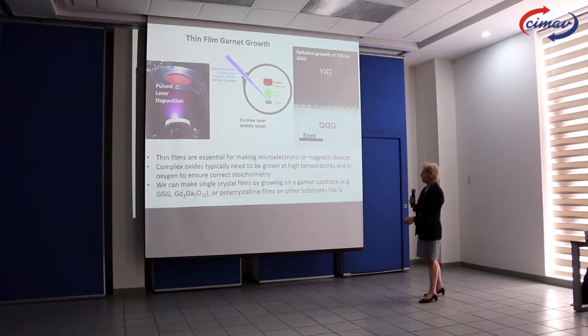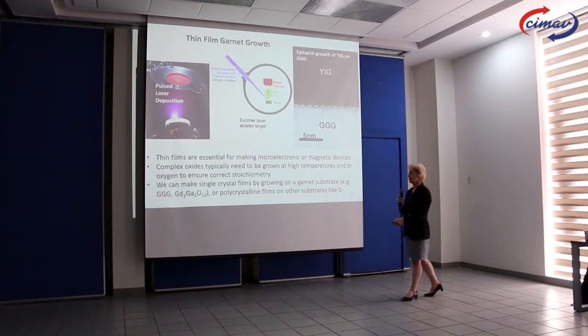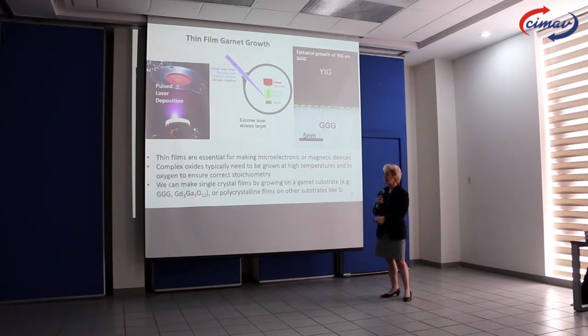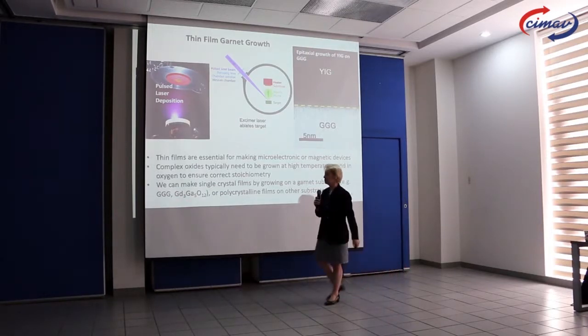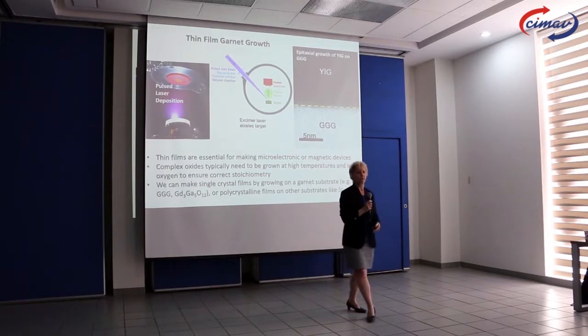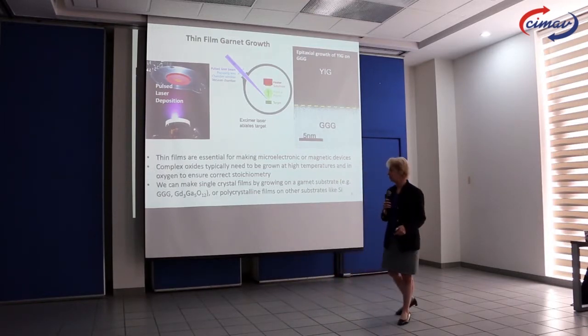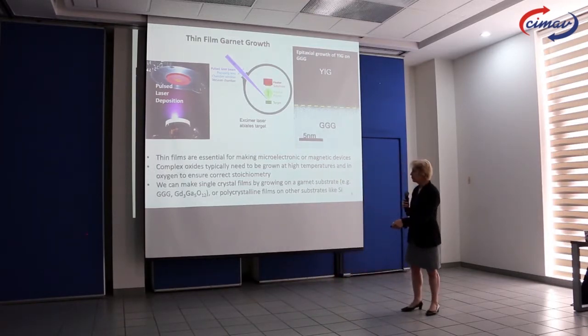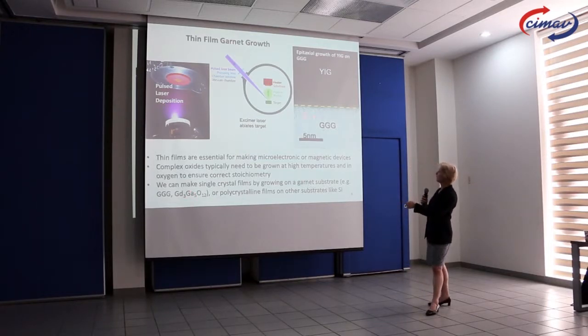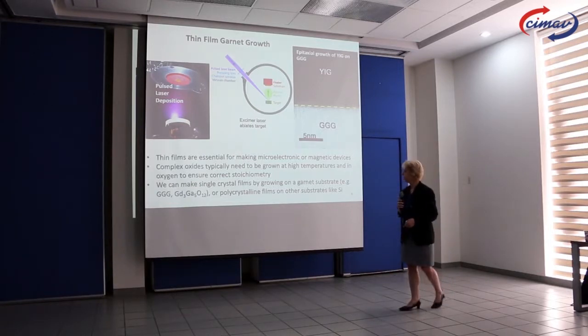And one thing I should say is that the common substrate that we use for growing garnets is called GGG, which is gadolinium gallium garnet. This is a paramagnetic substrate, because it has gadolinium in, but you can see the gallium there is non-magnetic. So the substrate doesn't usually interfere with the magnetic measurements. The reason we choose this is because it has a very good lattice match with YIG, so the crystal structure is continuous across the interface.